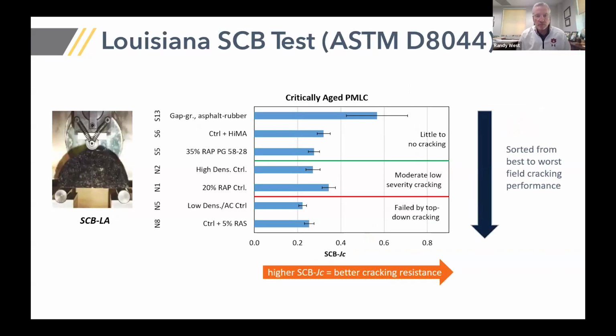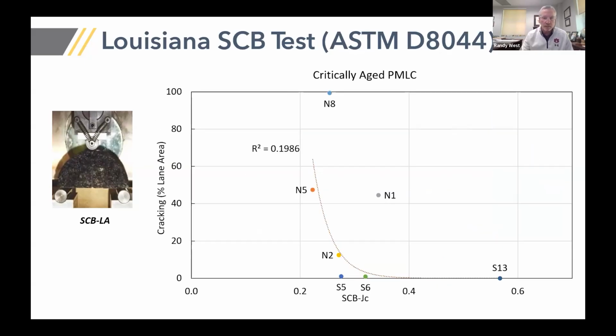Another test that is used by Louisiana is referred to as the semicircular bend test. And with this test, you can see it didn't necessarily do poorly in terms of ranking the mixes, but there are some cases where mixes with moderate to low severity cracking had better test results than mixes that performed really well. If we look at the correlation, the XY correlation, R squared is only about 0.2, and that's not a very strong correlation.